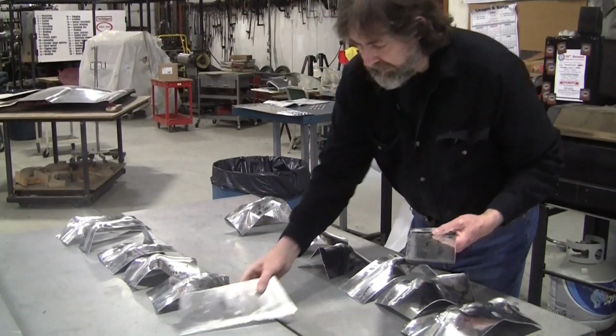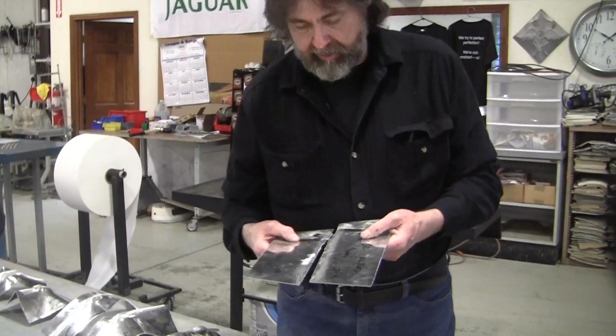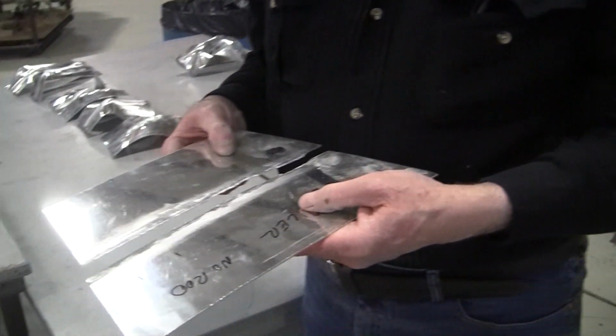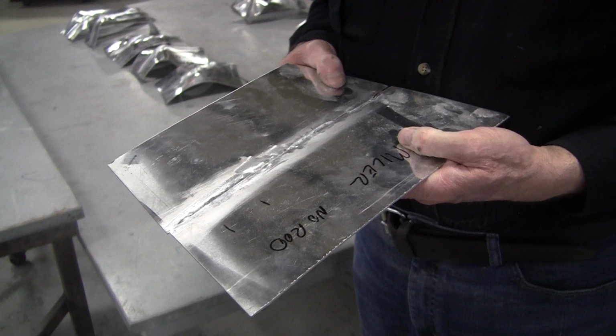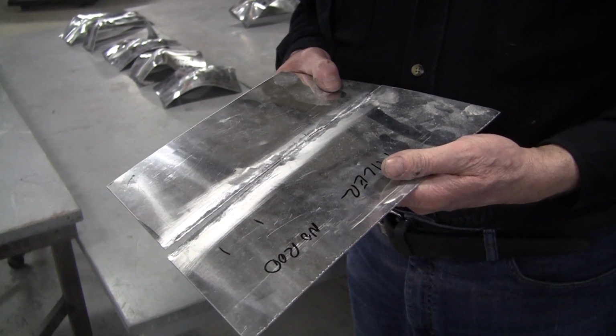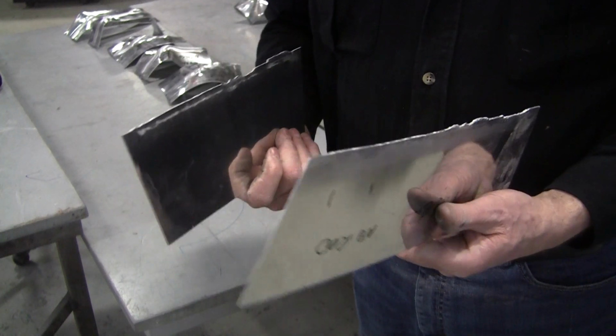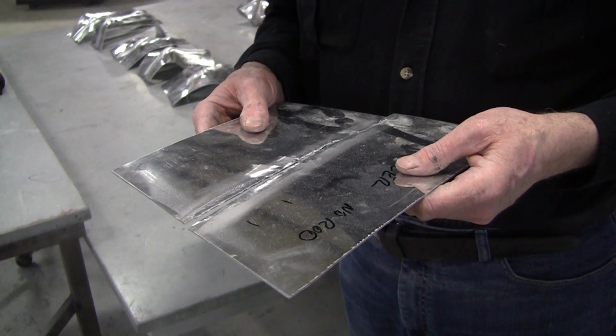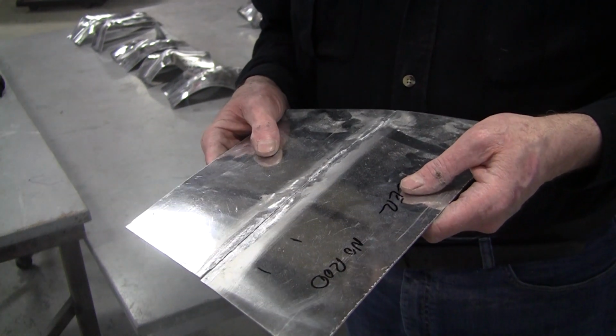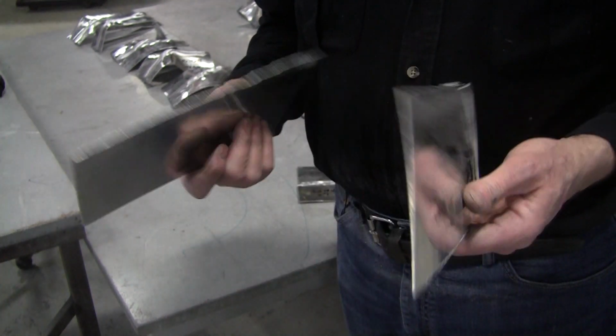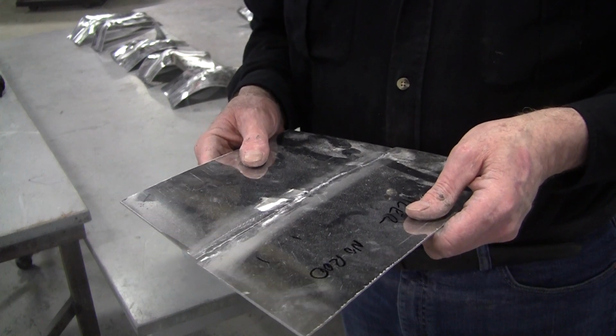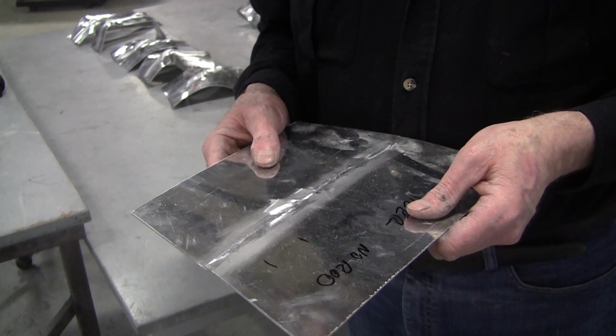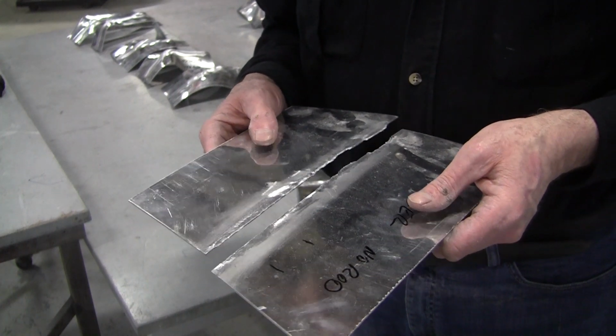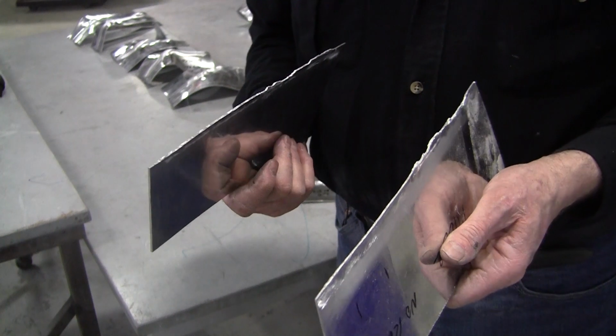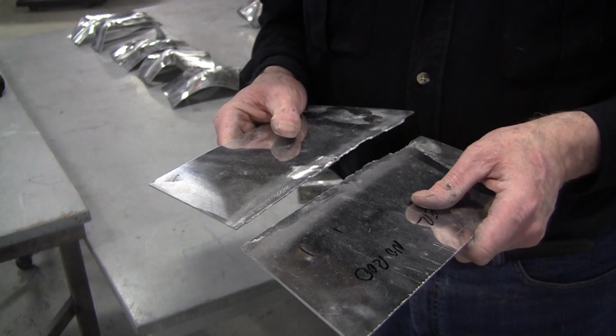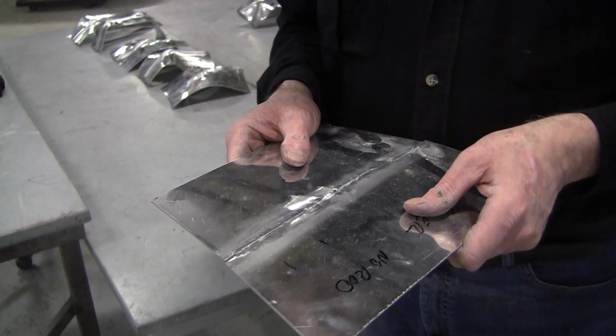This was the one that failed in video 2. It would be actually the series. This was a fusion weld with the Miller with no rod, and this just cracked right away and broke right off. And this will be your example. A lot of times you're going to see the same type of thing if you try to do that with no rod. I find that to be pretty constant. It's a hit or miss whether or not you're going to get a good weld there. I mean, it looked beautiful, but it just didn't have that full penetration, or handshake, I call it, solid weld.